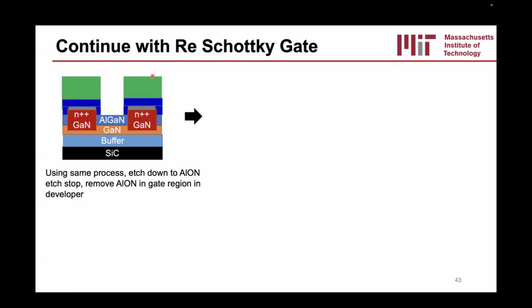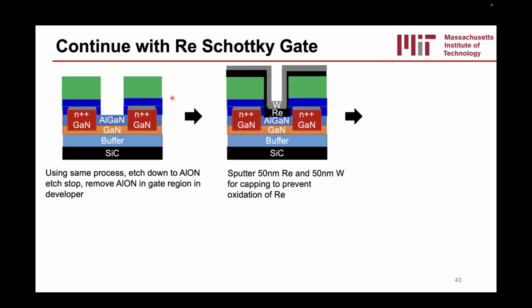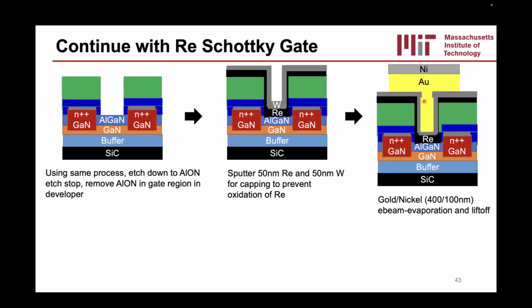So we can etch down the SiO2 with fluorine, stop on the aluminum oxynitride, and then remove the aluminum oxynitride in a little bit of developer, since the aluminum oxynitride etches very quickly in developer, while the AlGaN doesn't. Afterwards, we can deposit the rhenium, sputter the rhenium, sputter the tungsten, and then we can actually deposit some gold and nickel for kind of low resistivity filling metals.